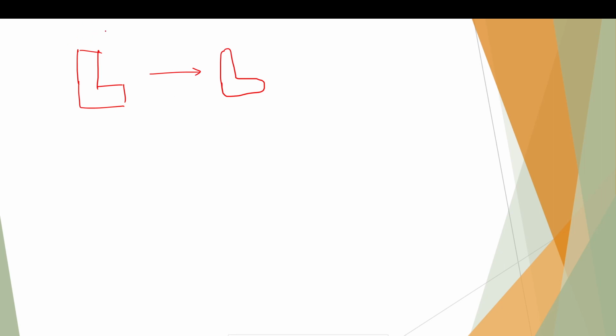So based on whatever is the pattern next to this, if you just look here, at this corner light can come from here. See, this is the mask, it's opaque, say, and also from here. So at the corner the exposure is higher compared to here, where the light can come only from this direction. So because of that there can be an edge rounding effect.